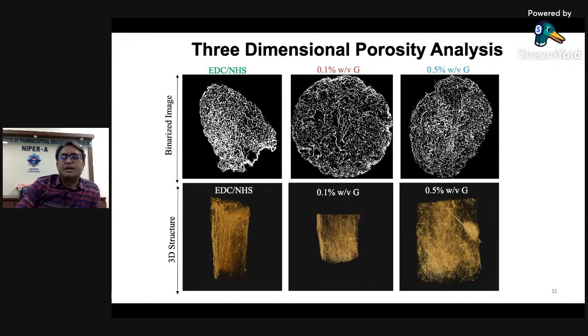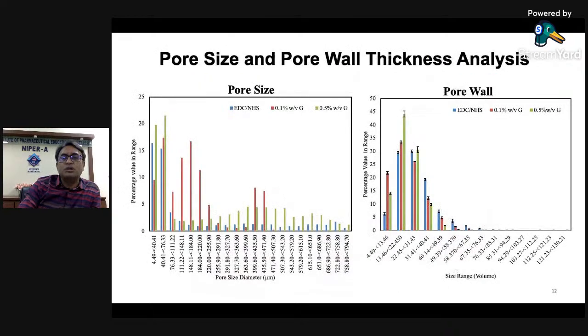Moreover, the porosity is much more controlled in the case of 0.5% graphene incorporation. The distribution is highly controlled, and most of the pore sizes are of the same size. Even the pore wall thickness is slightly higher. This means once the thickness of the pore wall increases, it imparts to the mechanical property.